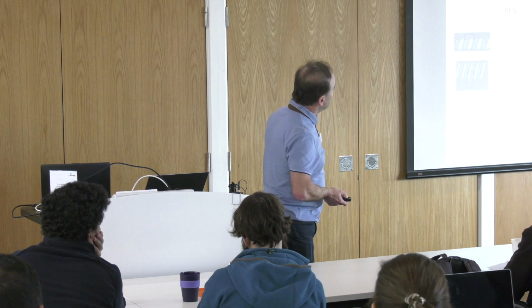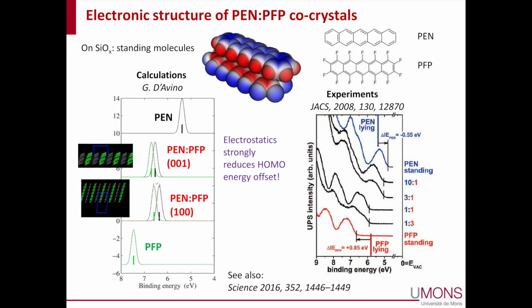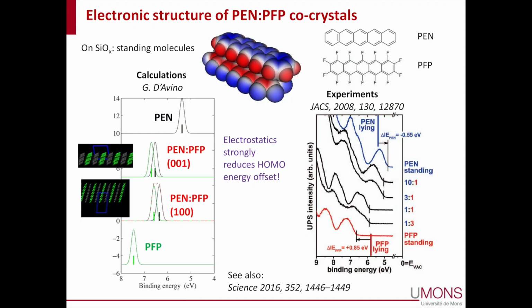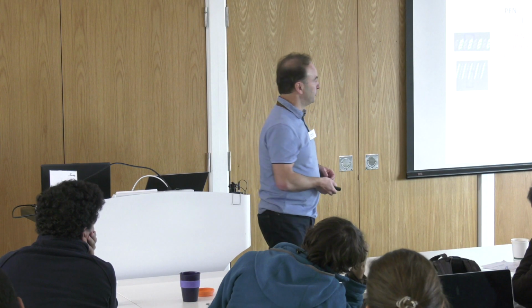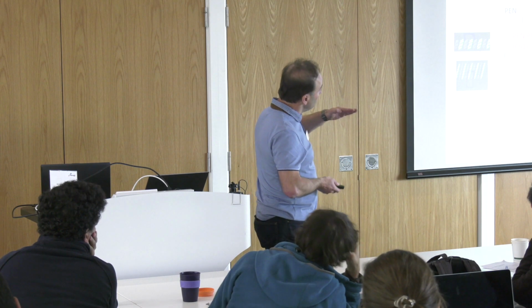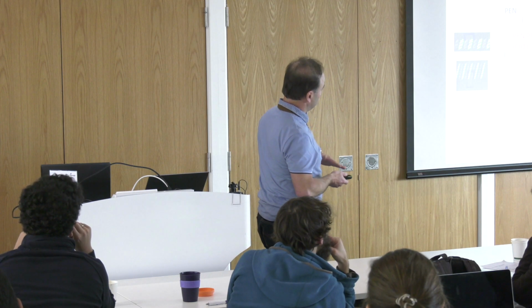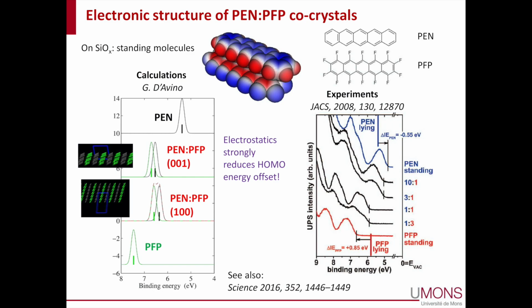And if you look at the UPS data of those co-crystals, while you would expect that in the mixed film you would have something that is intermediate, that is the superposition of the two molecules, which are shown here in blue and red, what you actually see is something that has a twin peak at an intermediate position between the two. So the energy levels of those molecules do not only depend on the molecules themselves, but strongly depend as well on their environment, especially the electrostatic environment. This is very nicely captured by the model. You can see this twin peak in the middle, and this is entirely driven by the interaction of the charge with the surrounding quadrupole moments, with the electrostatic environment. So that will, of course, dictate the absolute values of the energy levels, but possibly also the fluctuations, because as the molecules move around the equilibrium position, that will add some contribution to the energetic disorder.